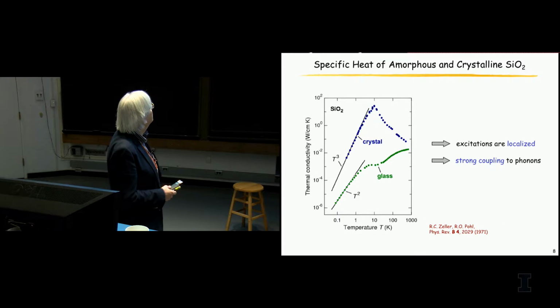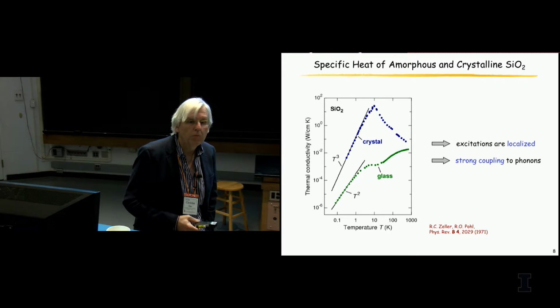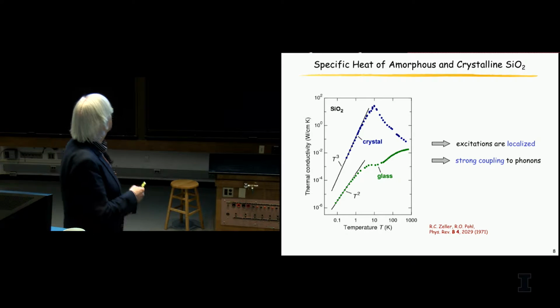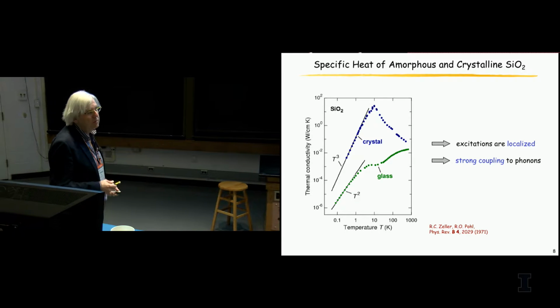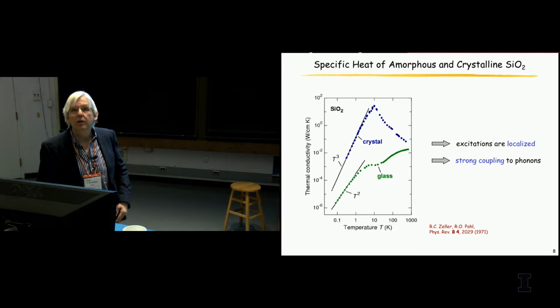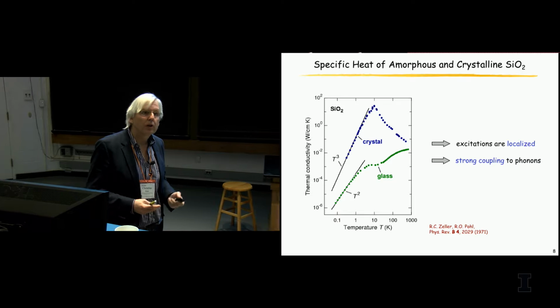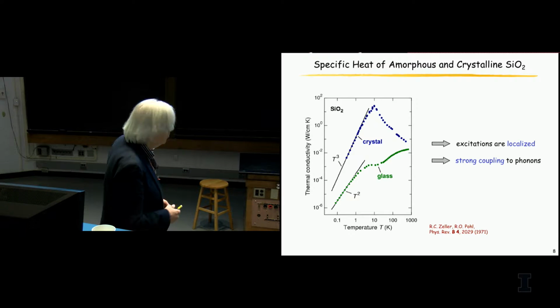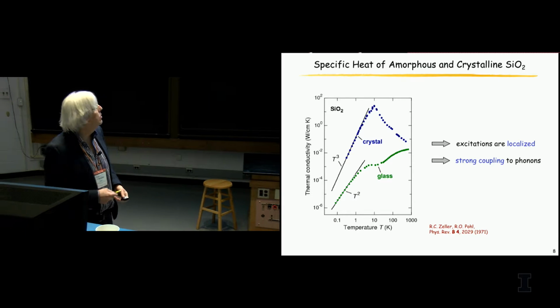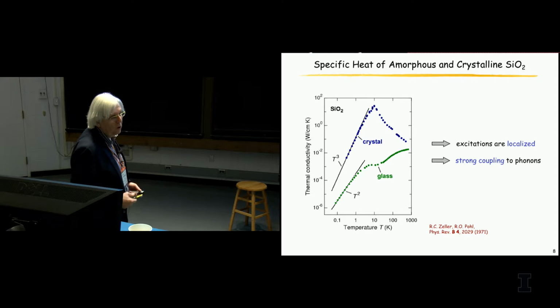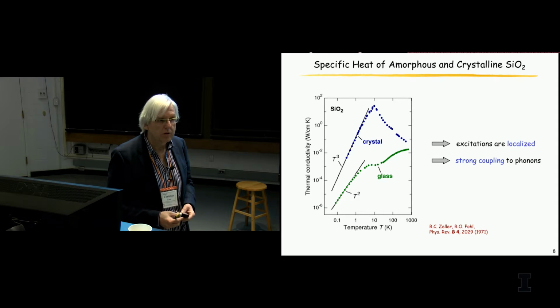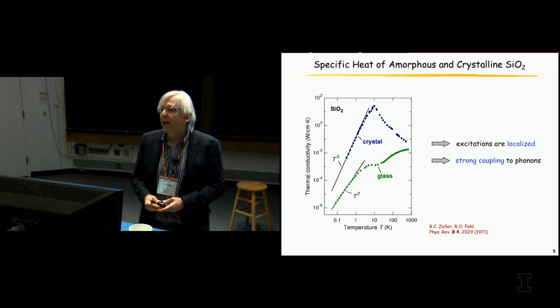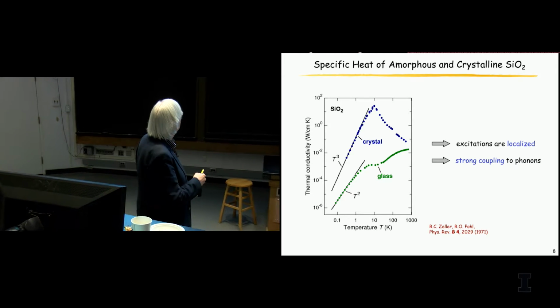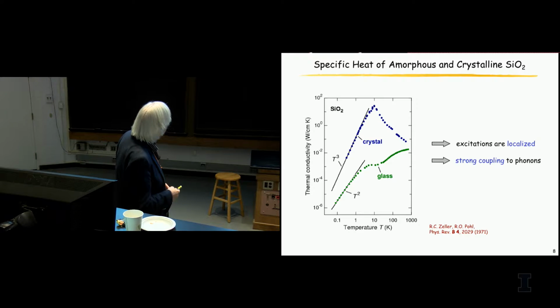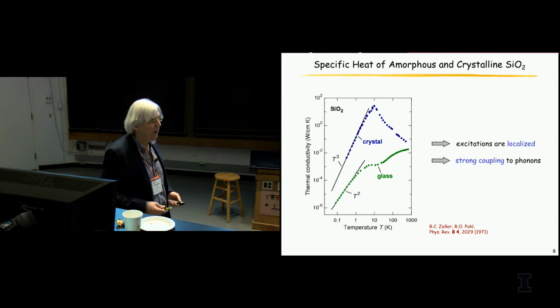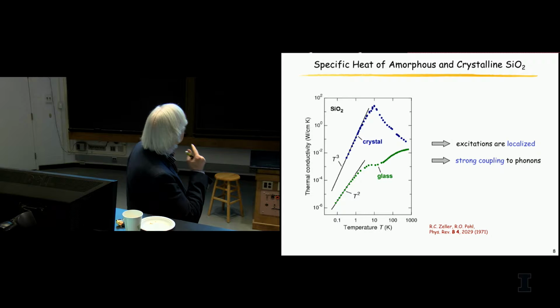Secondly, if you measure the thermal conductivity, you see that the thermal conductivity is much reduced compared to the crystal and has a different functional dependence. Peter was already pointing out this part here, where the phonons strongly interact with those low energy excitations. And the thermal conductivity as a function of temperature varies by T squared.